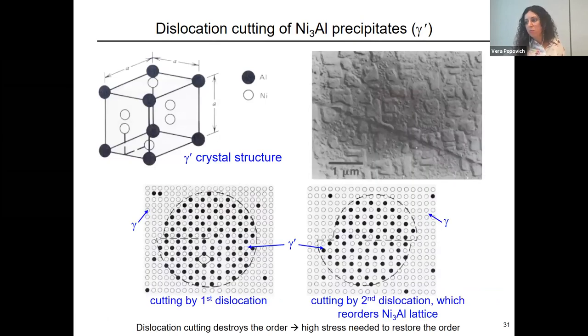Most of you here are probably not material scientists, so the crystal structure is of less relevance for you. But just to visualize this, when I'm talking about the ordered structure, this is an example of a crystal FCC structure, gamma prime, where you have aluminium at the corners and nickel inside. When a dislocation wants to cut, it needs to destroy the order of the atom positions, and the material would want to restore this order, which requires a lot of energy from the material.